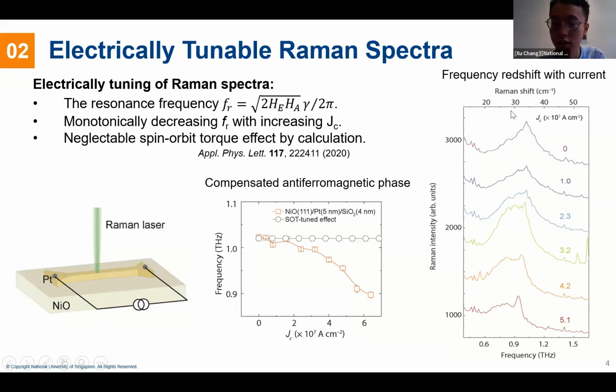But the frequency changes with our injected current, and it goes through a redshift. You can see the peak goes through a redshift. So our next question is, what caused this redshift? There can be quite a lot of factors, for example, Joule heating, SOT, and some phonon-mediated process.